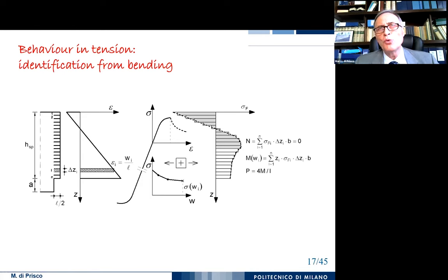And if we use the two equilibrium equations, due to bending rotation and longitudinal direction, and the plane strain approach that corresponds essentially to the Bernoulli idea for a homogenized and diffused portion of our beam, the portion between two cracks, in this situation we can arrive point by point to identify the constitutive law. But this way is very expensive in terms of time, and it's not good for design.